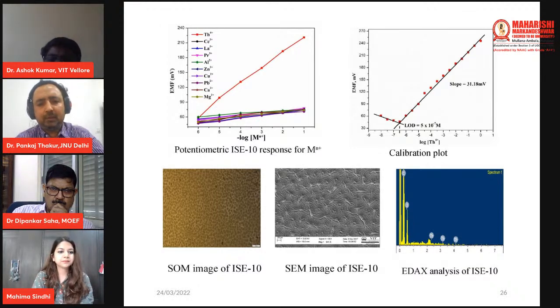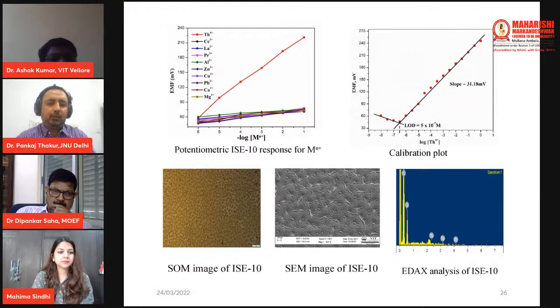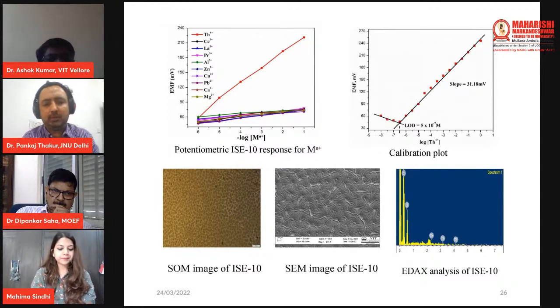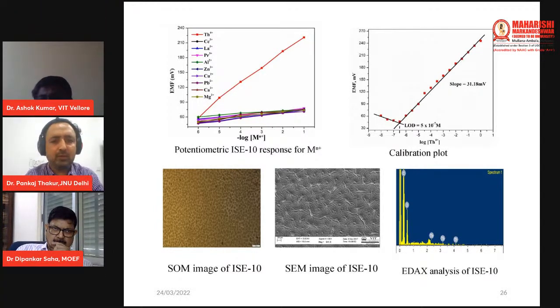No, sir. Here we want to see qualitatively whether thorium is there in the matrix or not. By taking this EDAX spectra, we just want to analyze qualitatively whether the thorium is bound to our ligand or not. I hope the thorium peak is the maximum? No, maximum for carbon, followed by oxygen, and the last three peaks are for thorium, because the thorium concentration is very, very small. That's fine.